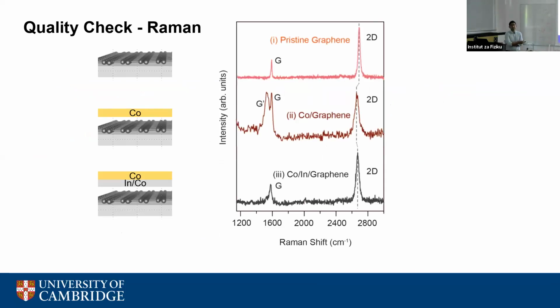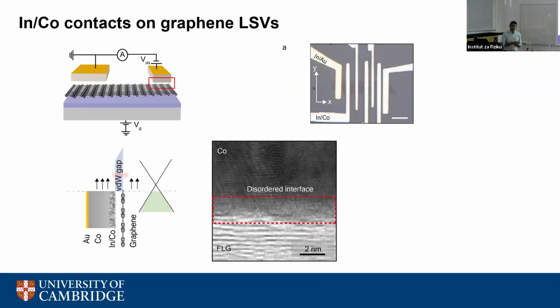Yeah. So the way we deposit them is, we use electron beam evaporation, where we have a substrate which is at room temperature. And we just use electron beams to evaporate out of a crucible. And the electron beam energy determines the kinetic energy of the evaporated atoms. By the time they reach the surface, we need to ensure they are not hot. So the trick is that we need to have an evaporator with a large working distance, where the evaporated atoms are not very hot when they land on the surface. Now, when you deposit gold or titanium, the evaporation temperature is slightly higher, and these hot metal atoms will cause these defects. But in indium, because the evaporation temperature is very low, around 150 to 200 C, the kinetic energy is very low, and it does not create the defects.